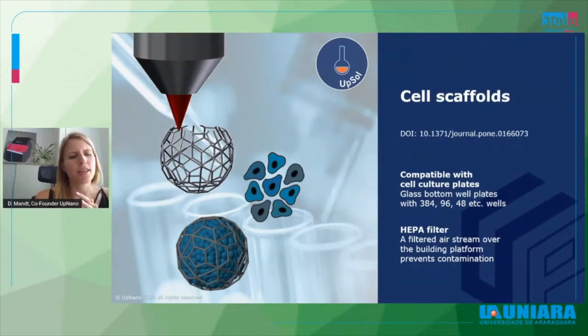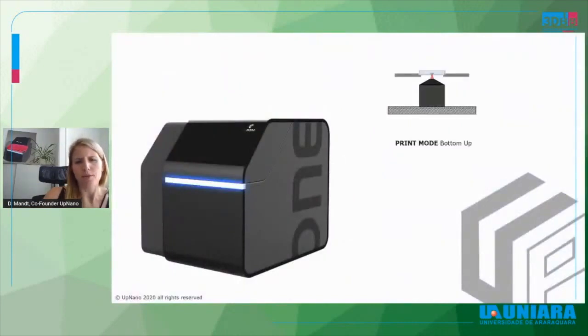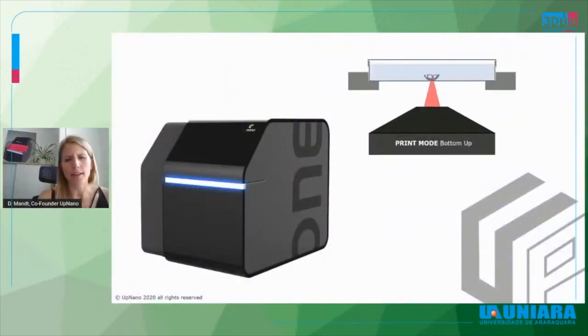This can be done in different vessels and configurations. Our goal was here to be very open and very flexible. So, for example, with the right insert, you can use cell culture plates, for example. The cell culture plate has to have a glass bottom with a 170 micrometer thick glass, because all the objectives are corrected to this 170 micrometer glasses. And then the scaffolds can be produced in the bottom-up approach we saw before. So beginning at the bottom and ending at the top.